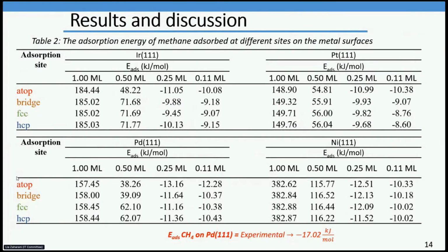The first adsorption site for methane is the atop site for all the metal surfaces, which agrees with related works. At coverage of 0.5 and 1 monolayer on the metal surface, the adsorption energy was positive, showing that the adsorption process was thermodynamically unstable. For methane adsorption on palladium 111, the most stable adsorption site was the atop site with adsorption energy of minus 13.16, which is in close agreement with the experimental value of 17.02.